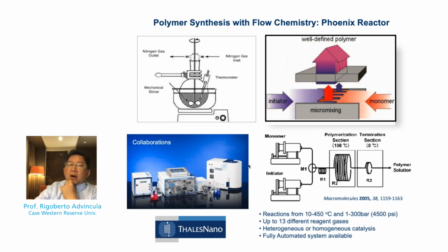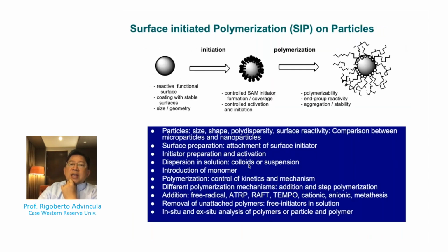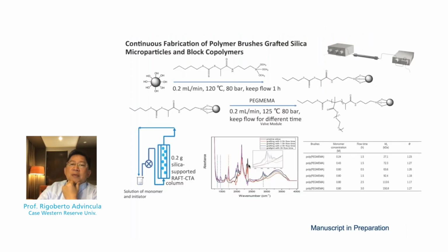So we have been working on coating particles with polymers using flow chemistry or batch processes. Basically, a particle can be coated with a polymer using surface-initiated polymerization. So this shell means that the polymer itself can be grown on the particle during polymerization. Now, we have demonstrated this using a flow chemistry setup where we pack the column with particles, and then we introduce the monomer, and the initiator has been previously grafted on the particles as shown here.